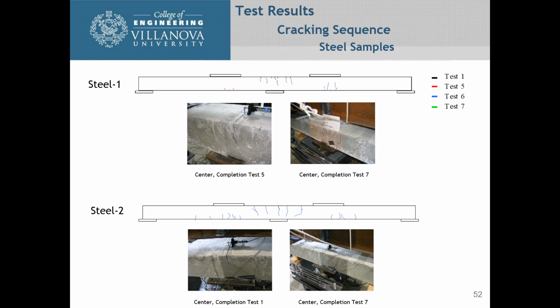After test 6, now you can really start seeing some cracking initiating on both of them. For sample 1, you see the cracking coming up from the positive area, and you see the negative cracking starting to extend. In sample 2, you could really see the cracking now extend in the negative and positive moment regions.